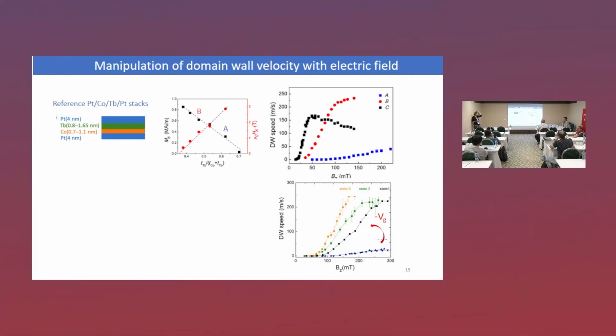So the problem about this kind of solid state device is that we had very small electrodes. The electrodes in this case were, I think, 10 by 20 microns, but we went down also to 1 micron, 500 nanometer electrodes. So once you have modified your structure below the electrode, there is practically no technique to look at what is happening, especially below 10 nanometers of dielectric layer. So we have to propose a model.